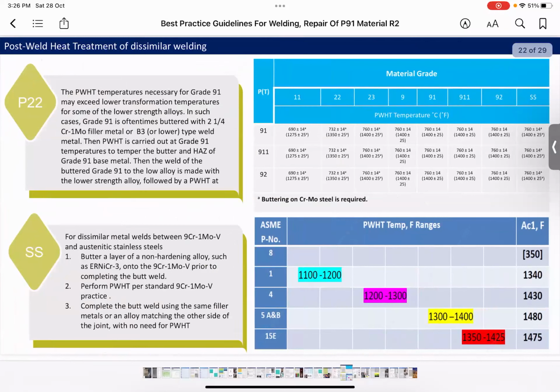So, post-weld heat treatment for dissimilar welding. As I said earlier, the welding for dissimilar weld is sometimes done using different grade, non-matching filler wire, like under-matching filler wire or nickel-based filler wire. So the PWHT, when P91 is joined to austenitic stainless steel, is done after the first buttering, and when joined to P22 material it is also done after the first buttering layer, according to this PWHT temperature shown here. These are the temperatures for dissimilar weld joints.